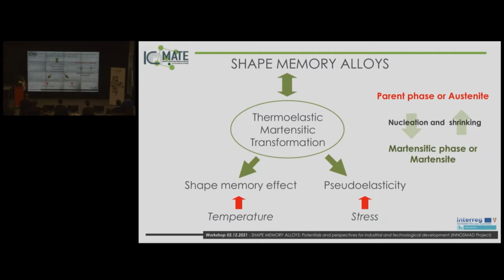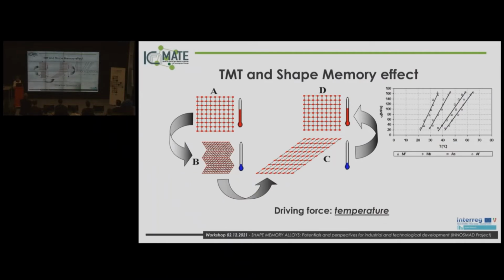This transition could be induced by two driving forces: by the temperature, and in this case we have the shape memory effect, or by the stress. In this case we have the superelasticity or pseudoelastic effect, which is related to thermoelastic martensitic transformation and shape memory effect. This is the schema to understand these functional properties. We can start from the austenitic phase at high temperature, and then we reduce the temperature, and the thermoelastic martensitic transformation occurs. And then in B, we have the martensitic state.